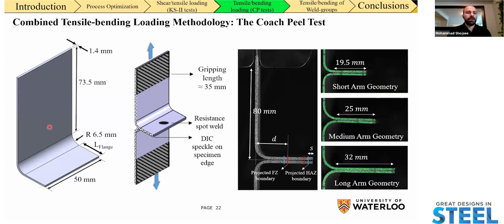You can see the coupon geometry. The coupon geometry is the same for all the geometries that we use, except the length of the flange. You can see a schematic of two of these L-shaped coupons being joined together, with the location of the spot weld here, and there's an offset between the axis of loading and the location of the spot weld. We coupled all of our tests with DIC again to track the evolution of all the forces and moments applied to the spot weld.